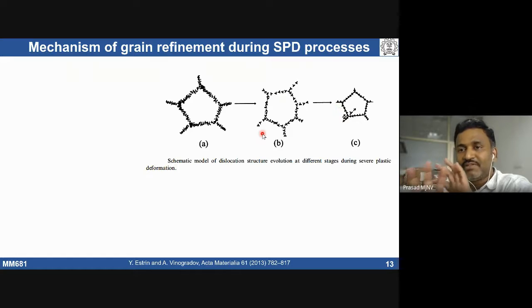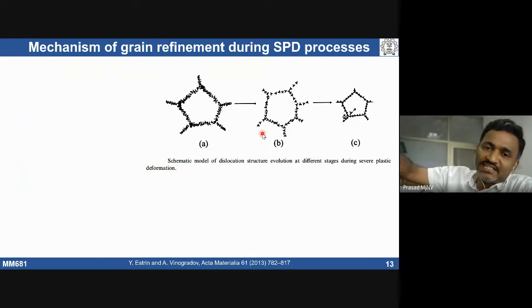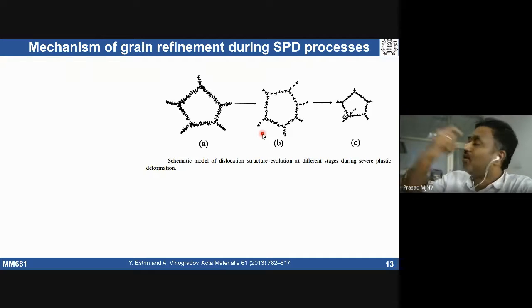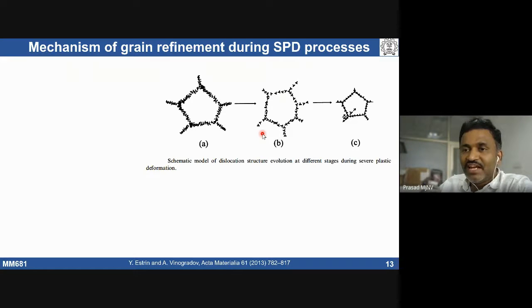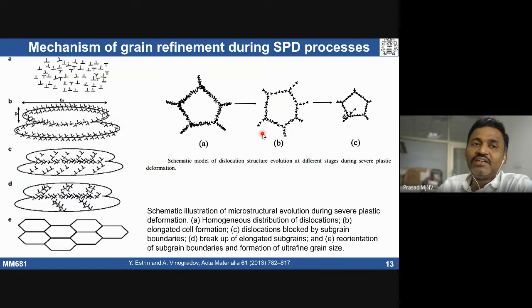We are talking about SPD, which is plastically deforming the material to very large strains. When you deform to large strains, there is a saturation of cell size, and the cells that are formed can undergo rearrangement. The dislocations get rearranged, leading to the formation of subgrains, and these subgrains can become full-fledged grains with high angle grain boundary character when you have more and more deformation. The same thing is given in a schematic picture: we develop a lot of dislocations during deformation, then a cell structure, which converts into subgrains, and with more dislocations we see the formation of a very fine grain structure.